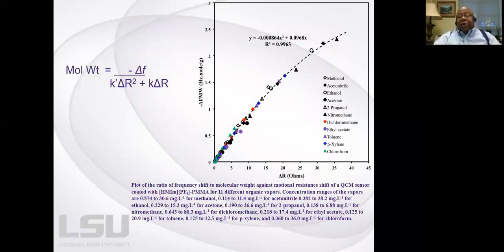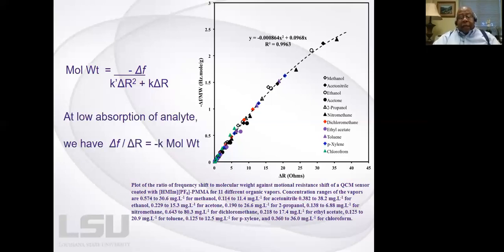And then we figured out that molecular weight must equal delta F over some term, delta R squared plus K times delta R. And so at low absorbers, delta F over delta R is equal to K times the molecular weight. So in fact, it's a nonlinear term in R, but at low concentrations, we get this relationship.